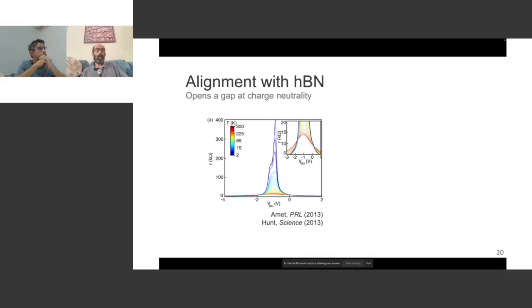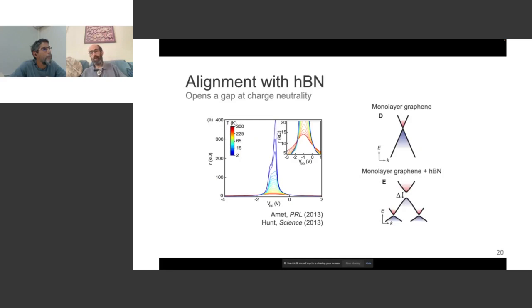And in fact, perhaps we shouldn't have been shocked that something should have changed when the boron nitride was aligned with the graphene, because my group and Pablo Jarillo-Herrero's group had both seen some years before that you could get very resistive behavior in graphene at the charge neutrality point when it was on boron nitride. Especially in Pablo's case, he showed that that was when there was alignment with the boron nitride, and that's associated with breaking a symmetry of the system that guarantees graphene is conducting at the charge neutrality point.